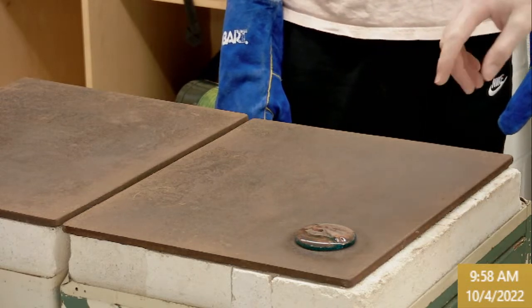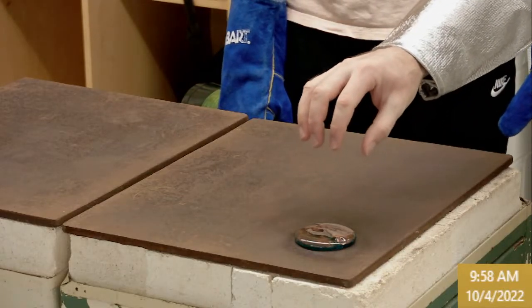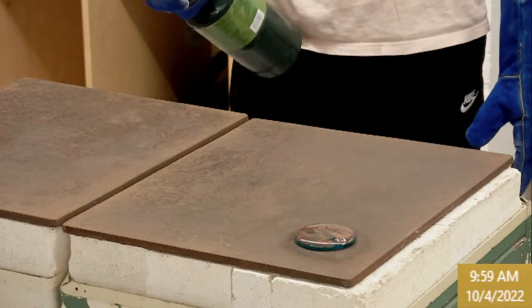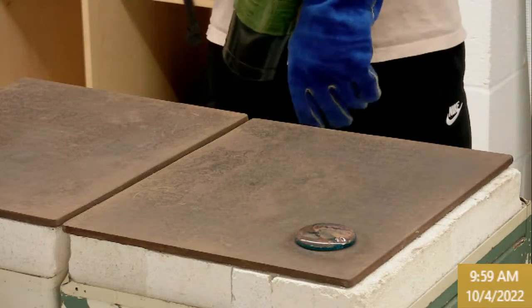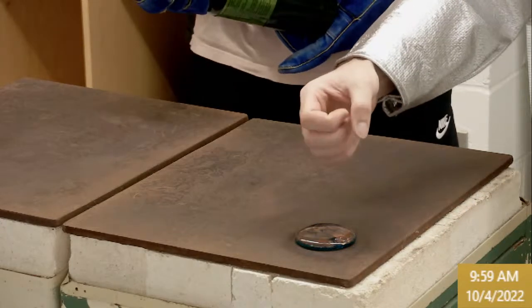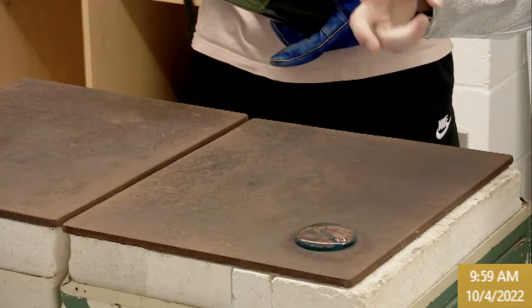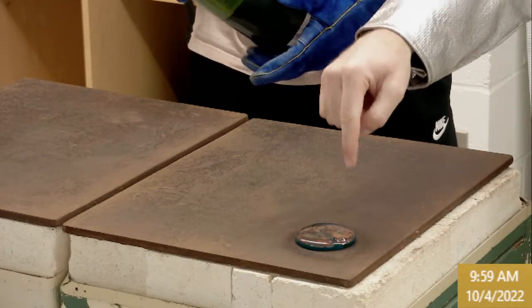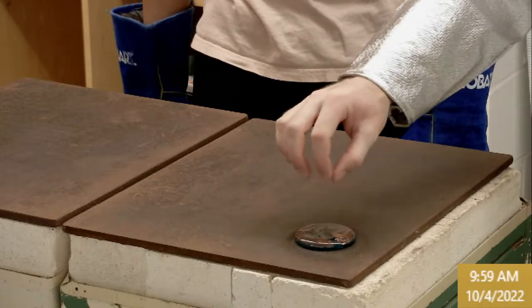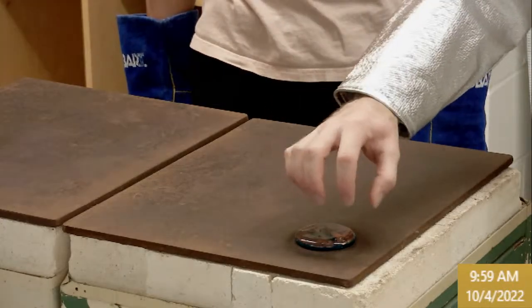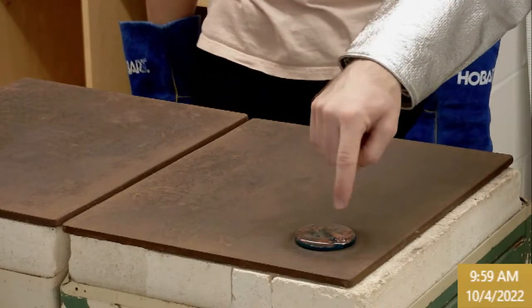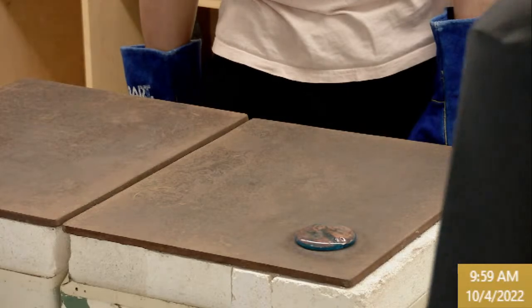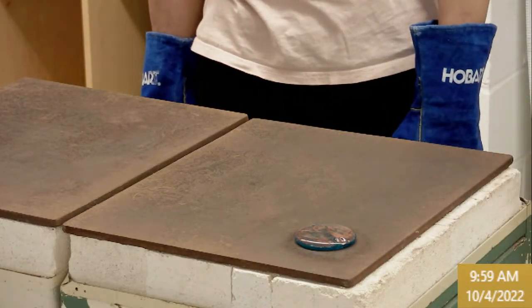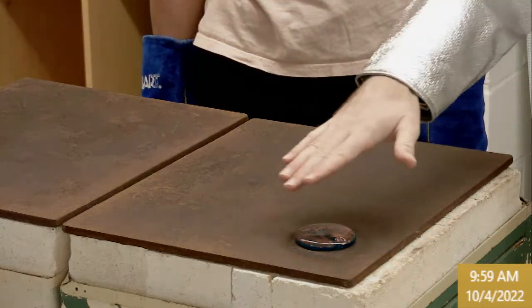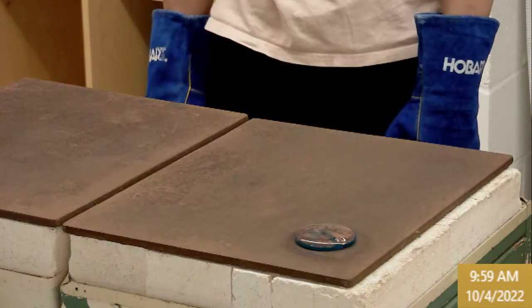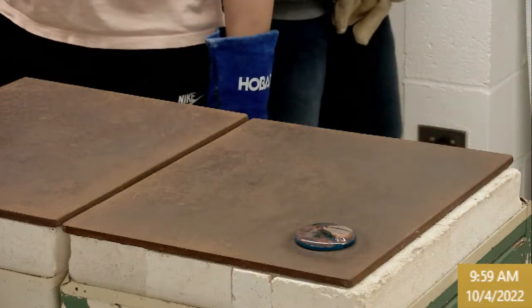There's also another interesting effect you can see on this one, and that is some copper mirroring. So this was copper. In the middle of this flame, there is carbon monoxide, just like we talked about with smelting. And the carbon monoxide is actually able to pull some of the oxygen from the oxide and donate electrons to copper. So we actually have some little metallic copper particles in the surface of the glass where the flame was kissing the surface there. So that's what this appearance is. And interestingly, it's such a thin layer, you can see it from the top, but when you hold this up eventually and look in the light, you won't even see that copper effect. It's a surface mirror effect. So kind of an interesting side note there.